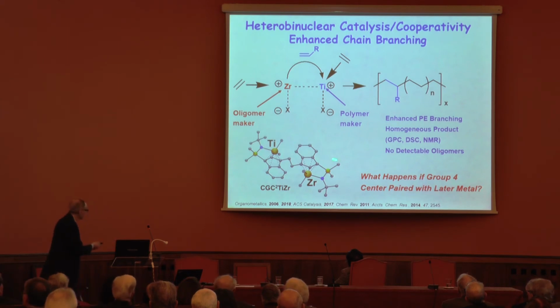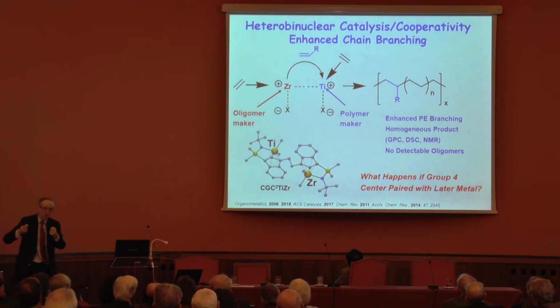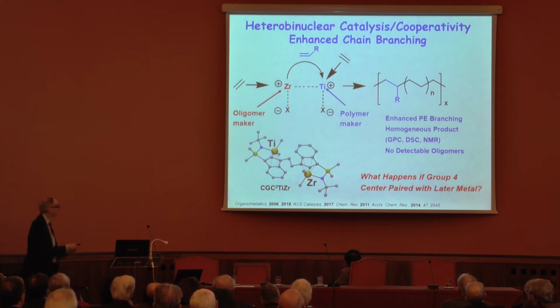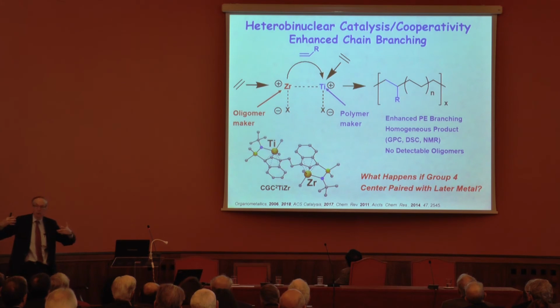And here's a very simple kind of structure. One titanium, one zirconium. The zirconium makes short chains. That's part of its chemistry. The titanium makes huge, long chains. And you put them in the same molecule, and each time the zirconium makes a short chain, you can't even detect this. It's captured by the titanium and makes some very unusual kinds of polymers. This R group then in the short chain becomes a long branch on the backbone of the polymer. Really interesting rheological properties, processing properties.